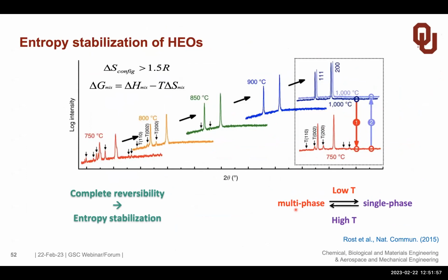What is interesting, and this is work by the group of De Maria, a PhD student called Rost, and they have looked at this identical system and published this in 2015. And what they have proven is that this is really entropy stabilized. So if you look at the free energy of a system, it has the enthalpic part, but also a part of the entropy. And the dominant part, if you go into this system, is what is called the configurational entropy.